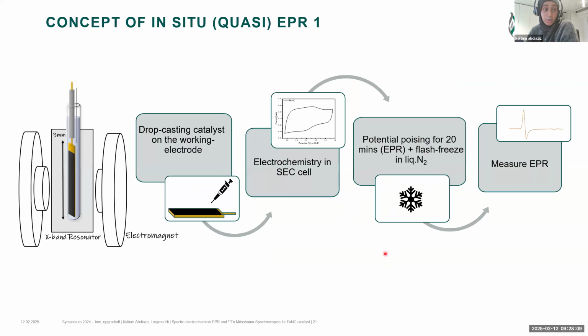The way I do these experiments is I drop cast my catalyst, or whatever it is that I'm working on, onto the electrode, and then I assemble my setup and measure the electrochemistry inside the spectroelectrochemical setup. I then compare this with the exact same system in a standard electrochemical setup to make sure that there are no differences between the two. I then apply a potential, usually for about 20 minutes, but this can be reduced. Then I flash freeze this in liquid nitrogen, and I wait for the current to go back to 0 to indicate that everything is frozen. Then I take my sample to the EPR spectrometer and I measure.